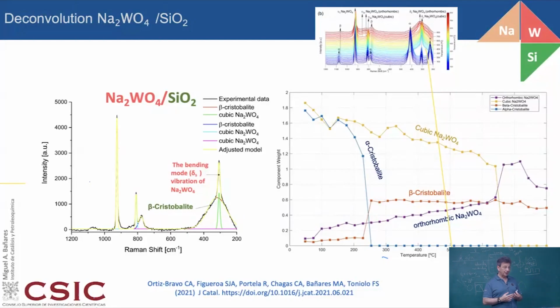And then you are looking at the hydrocarbon species, at the oxygen species, and you have to tell apart which ones are spectators, which ones are active ones, and that requires some kind of dynamic system. Some dynamic systems, like for instance steady state isotopic transient kinetic, was an approach where basically you have a reaction, and in the steady state isotopic transient kinetic, what you do is not on and off, is that you have maybe toluene on both sides, but here you have toluene with carbon-13, and here you have toluene with carbon-12. So what happens is that by doing the switch, and you make one switch, the reaction is exactly the same. Actually, the reaction is not even aware that you have made a change, but then all of a sudden, one of the molecules comes with a different isotope.